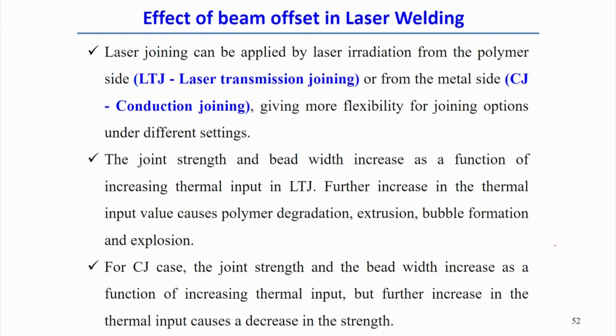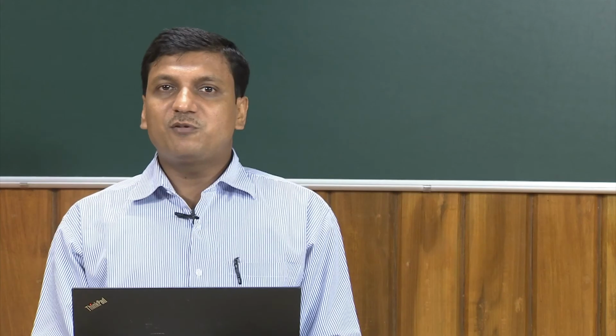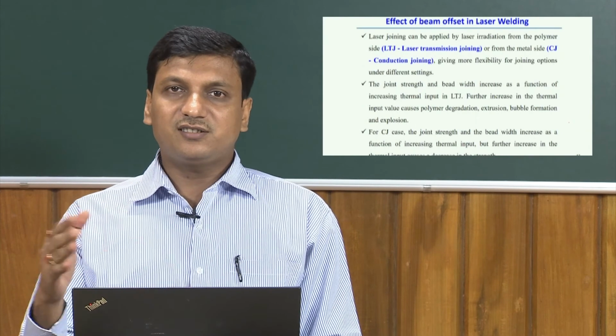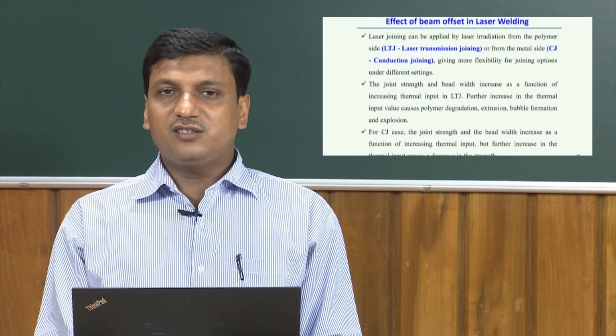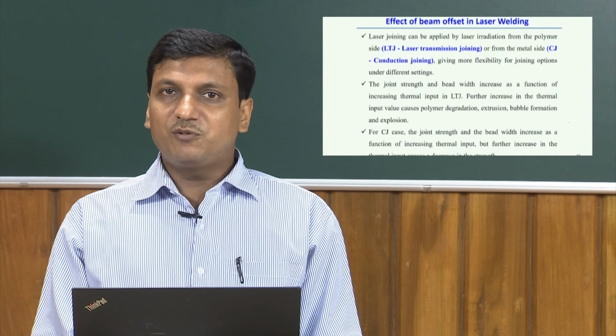It is observed that the joint strength and the bead width increase as a function of the increasing thermal input in laser transmission joining. So, if you increase the thermal input, the strength can be increased, but if we increase it too much, there may be degradation of the polymer, and bubble formation and explosion can also happen. So, we need an optimum amount of energy such that the joint strength can be optimum between the polymer and the metal.